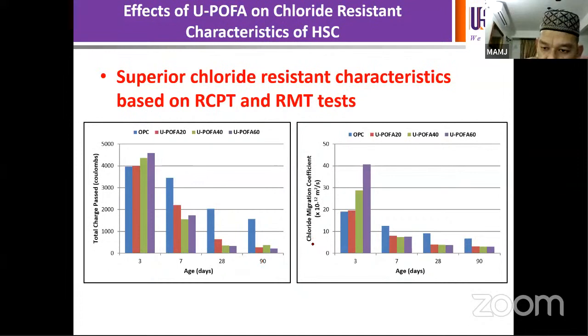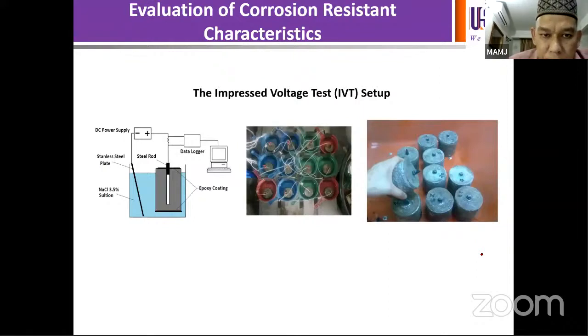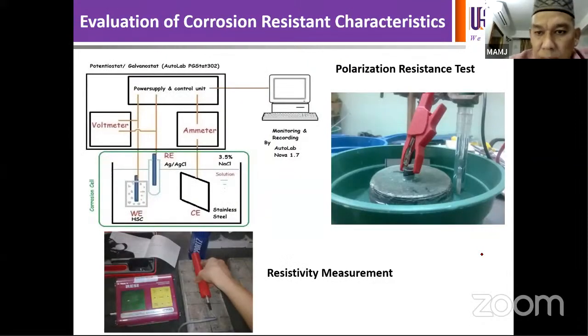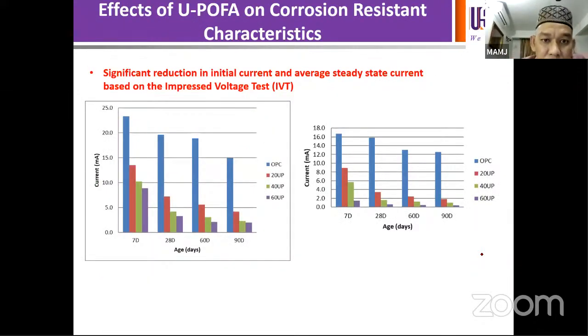Okay, so similar but slightly less effect in the case of chloride migration coefficient, but in general, especially at a longer curing period of 90 days, the concrete containing UPOFA here exhibits lower chloride migration coefficient in comparison to the control concrete. Okay. So some tests related to corrosion resistance characteristics were also undertaken. So based on the impressed voltage test, IVT, here is the setup as well as the polarization resistance test and also resistivity measurement. So here are some of the outcomes of the corrosion test.